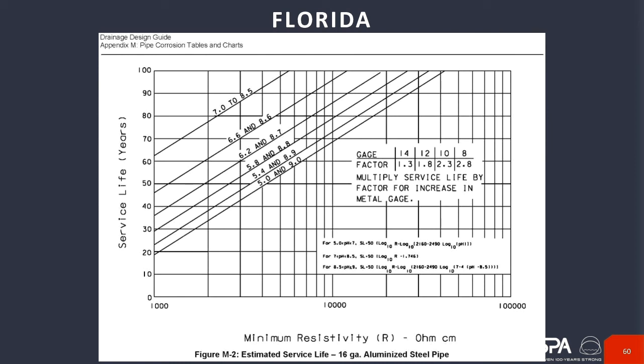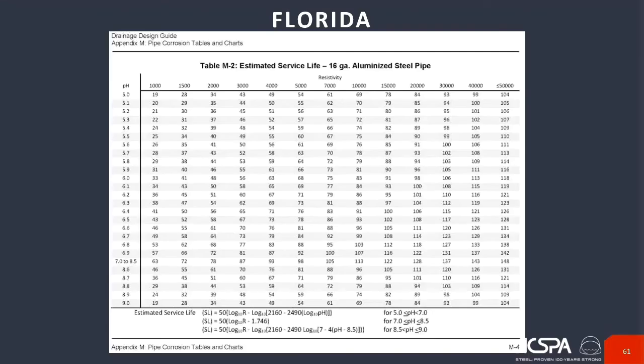So back to Florida. So Florida has developed curves of its own. This particular curve is for aluminized steel, aluminized type 2 pipe. And as you can see, it's very similar to the pipe for galvanized developed by both Caltrans and AISI. So pH and resistivity are the primary drivers. And then you have your gauge factor here. So 16 gauge would be the base gauge. And then you can multiply it by 1.3 and 1.8 to get the service life for the other thicker gauges.